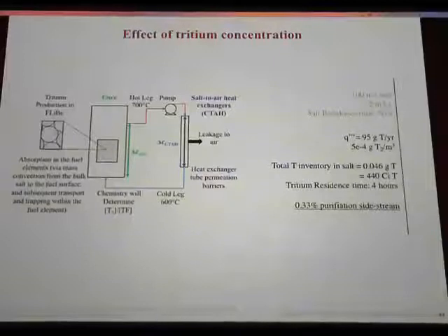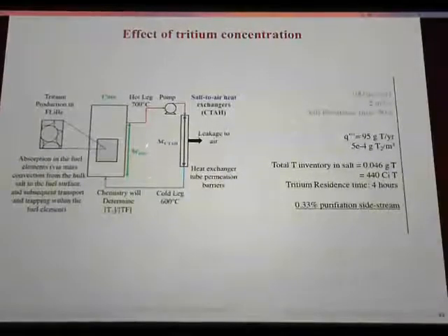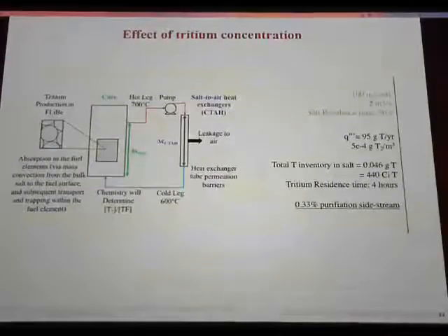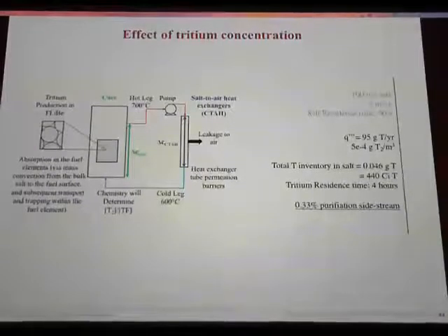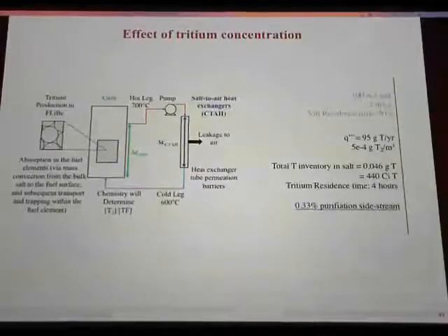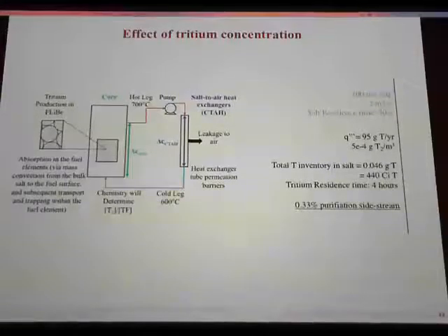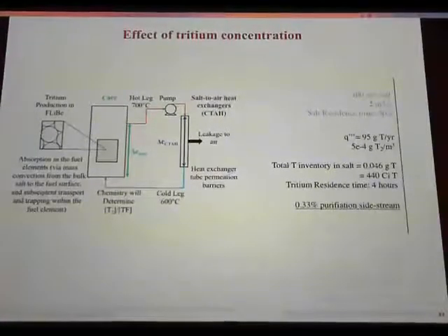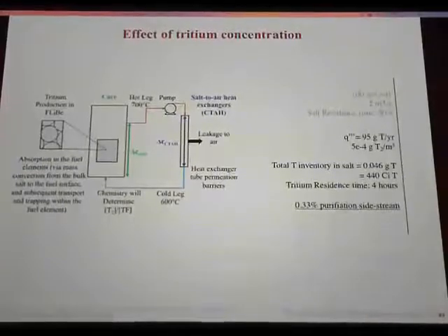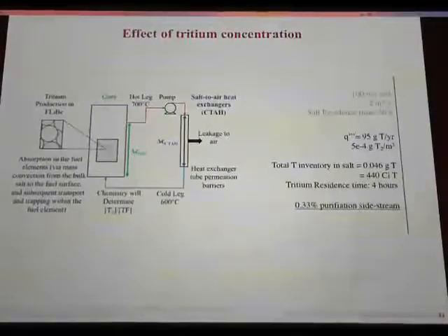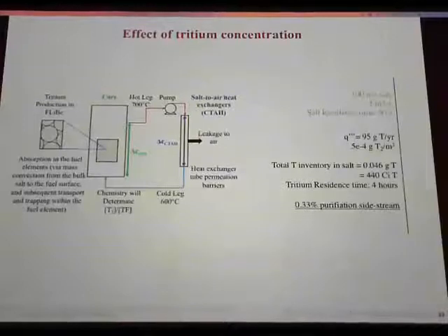Now another thing that a higher concentration of tritium in the coolant does is it gives you a larger term for the mass transport. So if you want to transport tritium from the bulk of the salt to the surface of your fuel elements, there's a mass transport resistance there, and the higher the concentration gradient, the easier it is to remove.